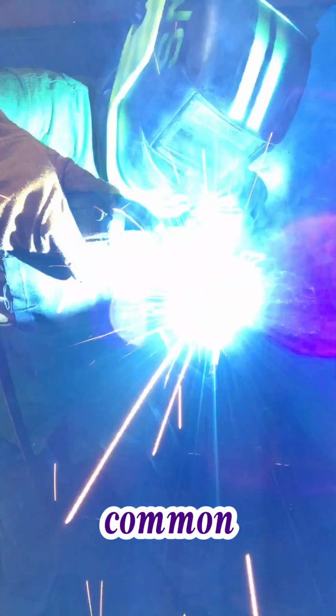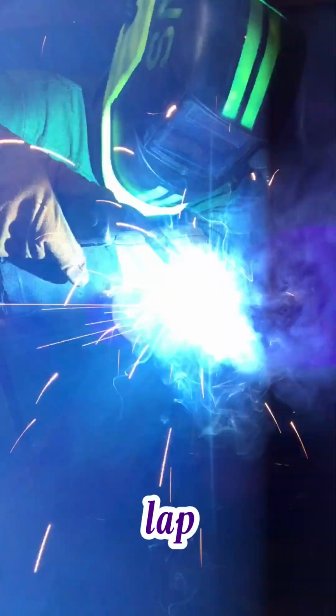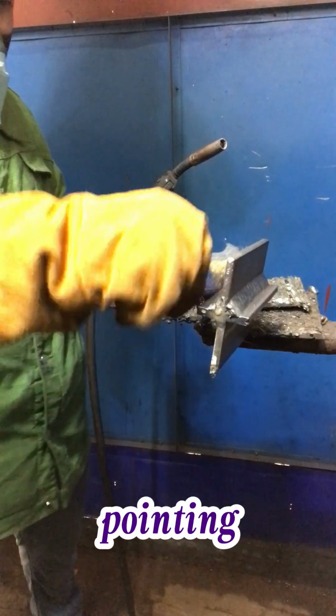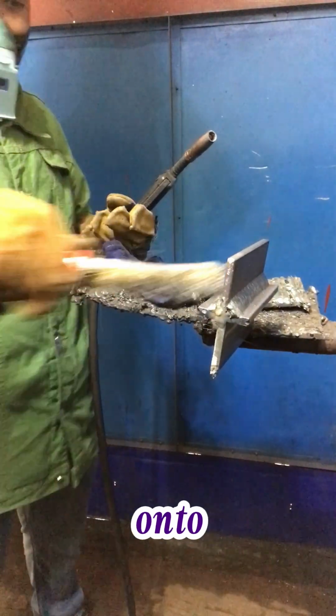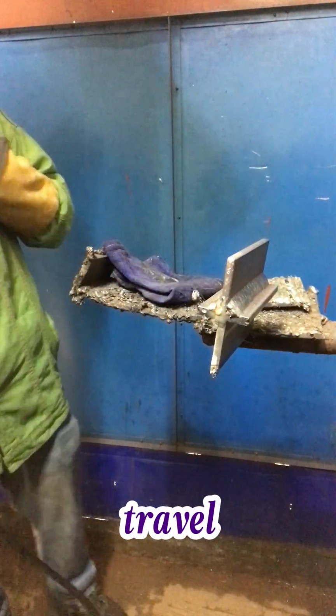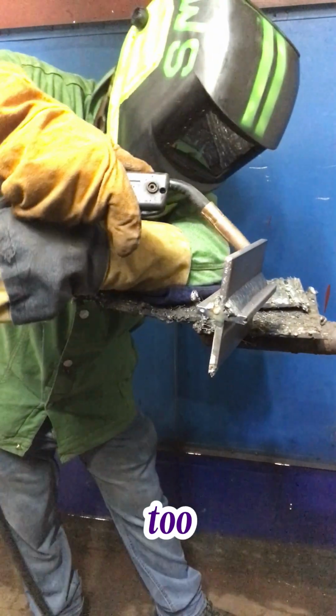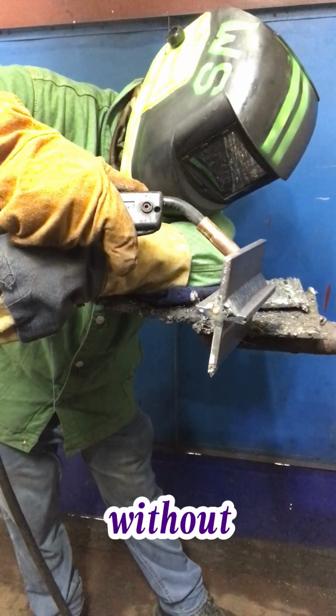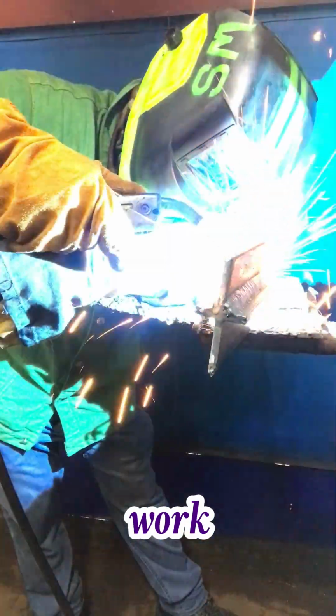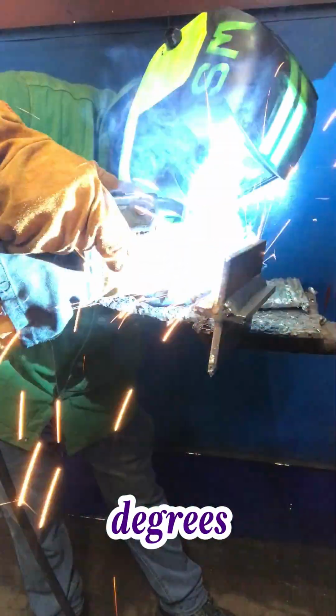Managing common beginner errors. Cold lap, sagging: moving too slowly, or pointing the gun too low causes metal to droop onto the bottom plate. Increase travel speed. Undercut on vertical plate: pointing the gun too high or moving too fast eats away the top plate edge without filling it. Adjust your work angle back to 45 degrees.